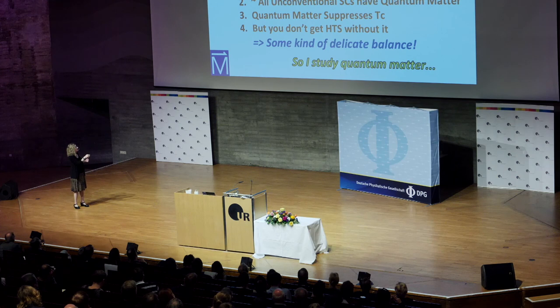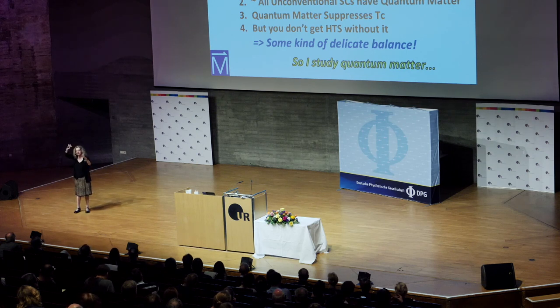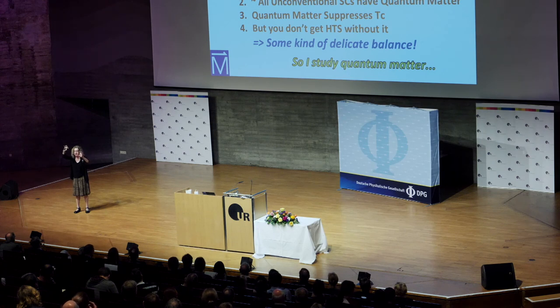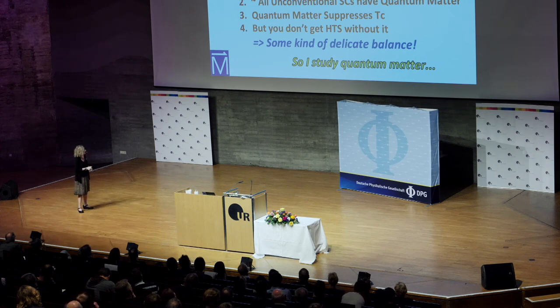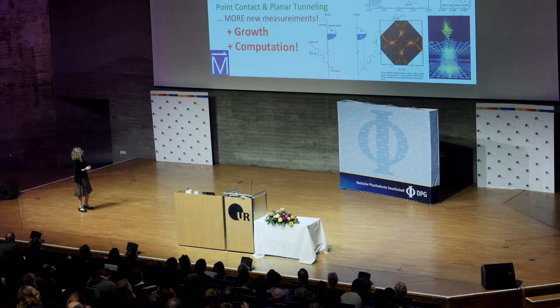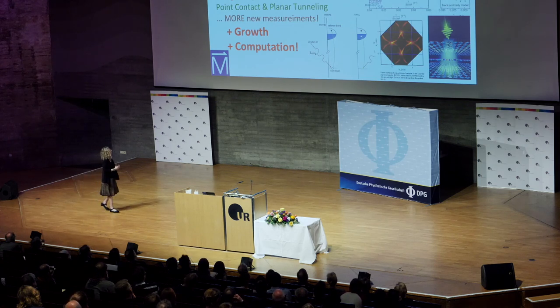So if the correlations are too weak, superconductivity is not as strong. Somewhere in the middle, it's the highest Tc. Even though the correlations will kill Tc, you don't get high Tc without them. There's some delicate balance going on. I work on this all the time when I'm not doing policy and other things: you have some kind of strong correlation at high temperature, and at the right level, that breaks into the pairing underneath the superconducting dome. And that's what I study now.